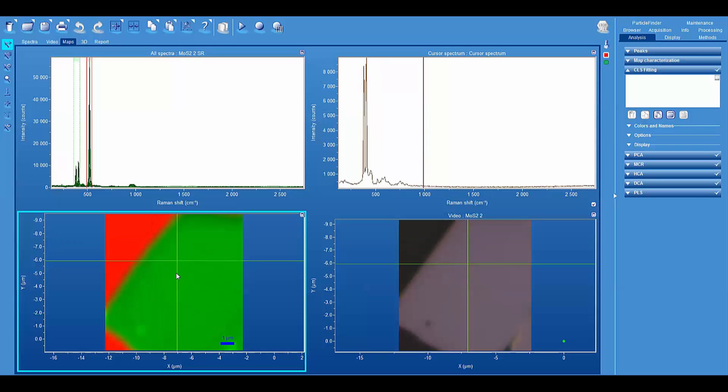So the important consideration right here for you is that the image was generated in 300 nanometer increments with one second integration time. And so this entire image took 22 minutes and 59 seconds to generate. And this is what you see using the peak bracket method.